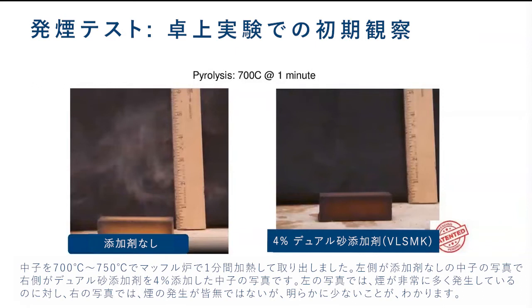On the left side, you see the no additive. We try to help the eye by putting a black background and a ruler. And you can see that the no additive shows a significant amount of smoke. And on the right side, we have our dual engineered sand additive at 4%. It's not completely 100% smoke suppression, but definitely there is a significant amount of suppression of the smoke in the presence of this sand additive.